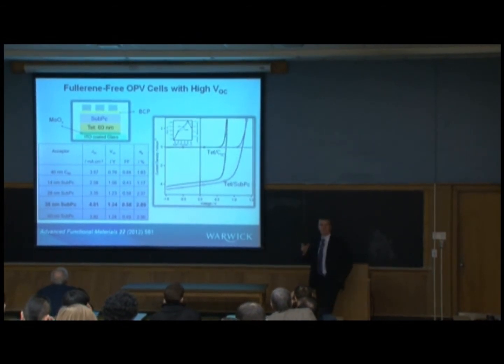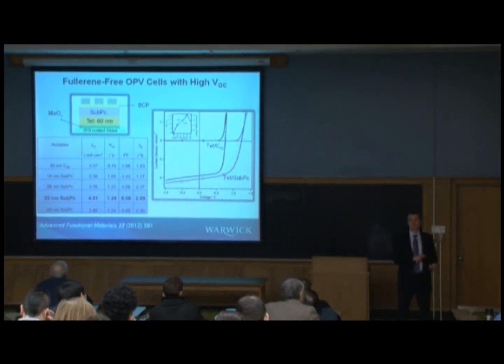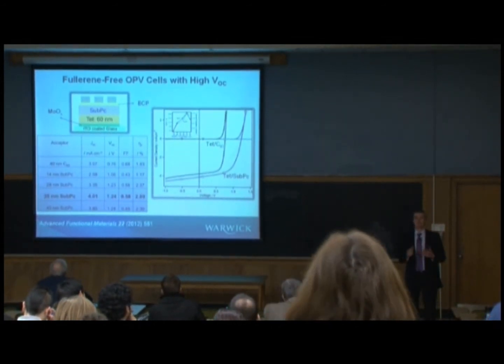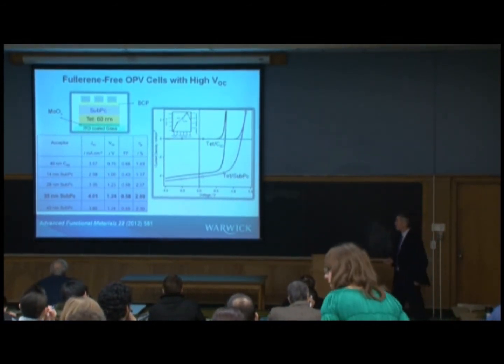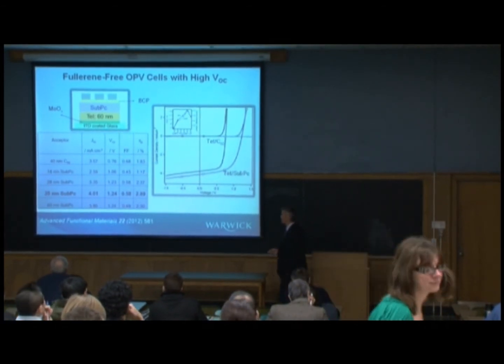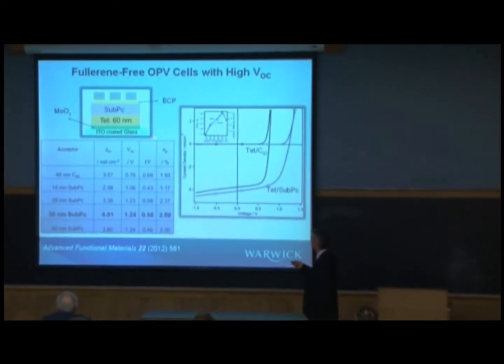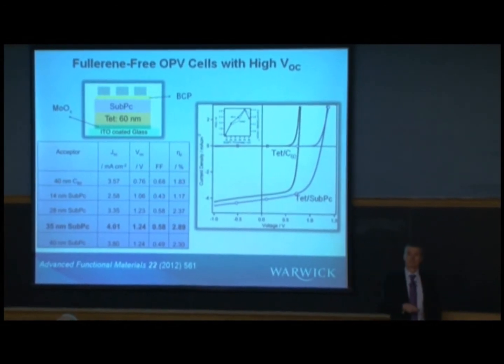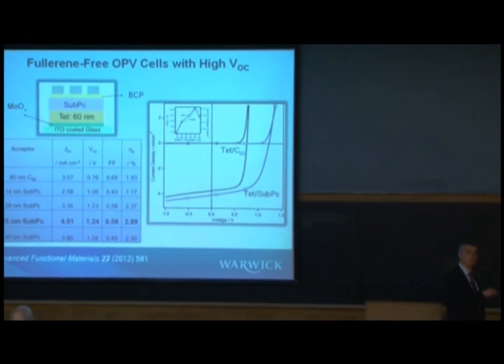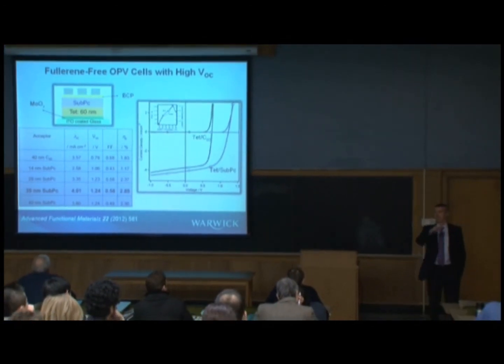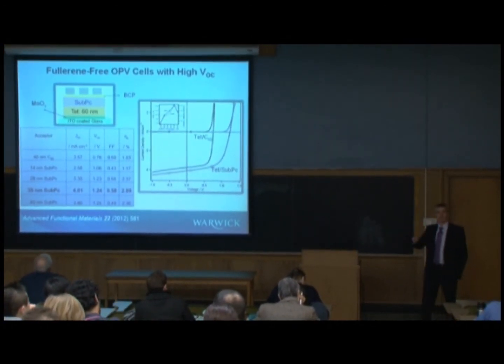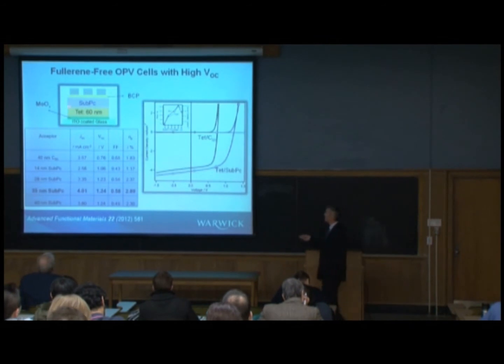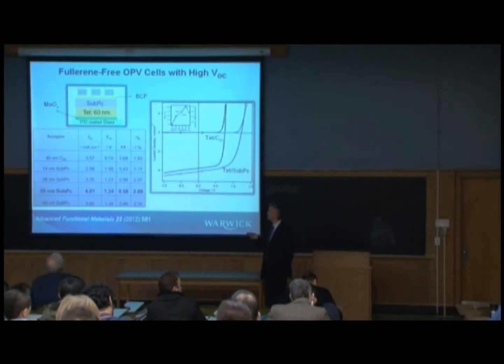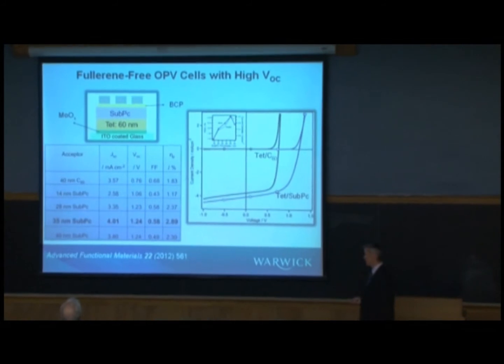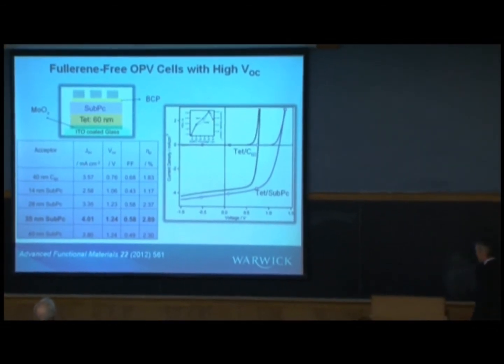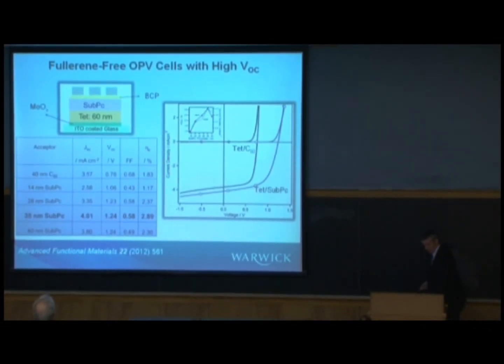So if you tailor the materials, you can now use materials that conventionally have been used as donors, as acceptors, or vice versa, in order to optimize some of the parameters of your solar cell. And one actual advantage of this, I don't have the plot here, is that sub-PC is much more stable than C60. If you look at the stability of devices with C60, they degrade very rapidly without encapsulation, whereas the devices without the C60 are actually much more stable in this particular case. But the key point here is you can increase the voltage very significantly.